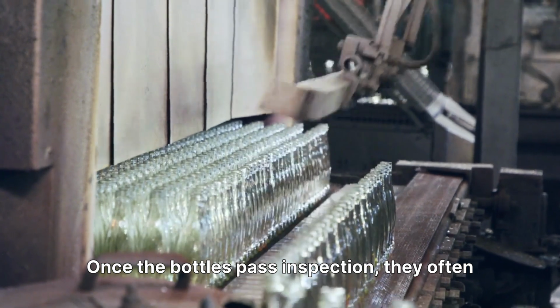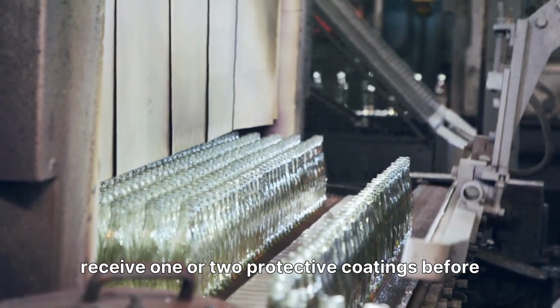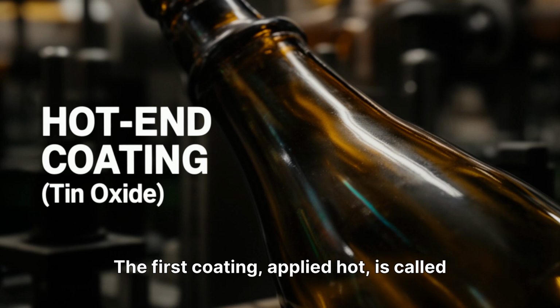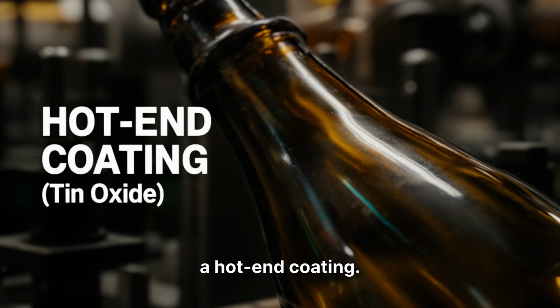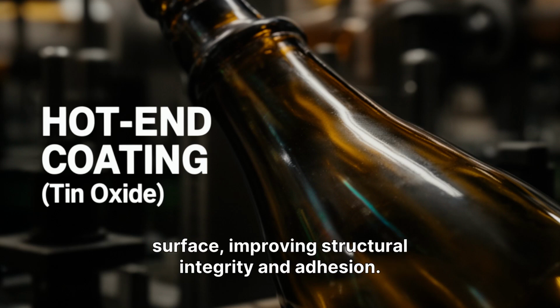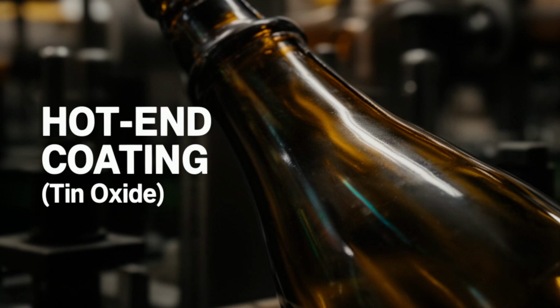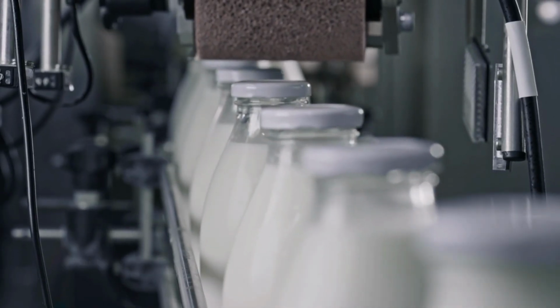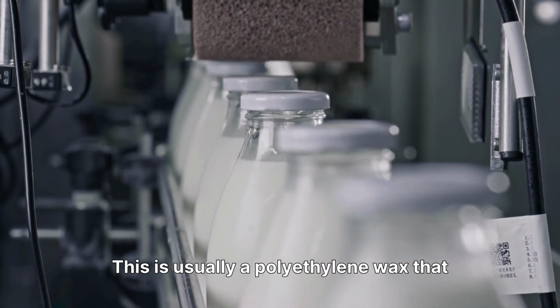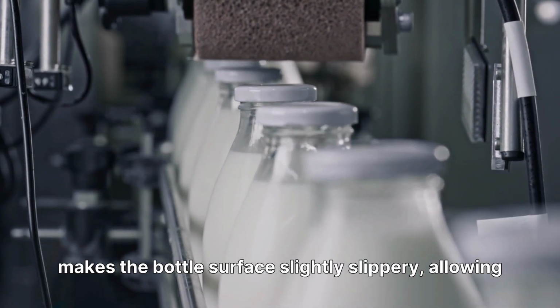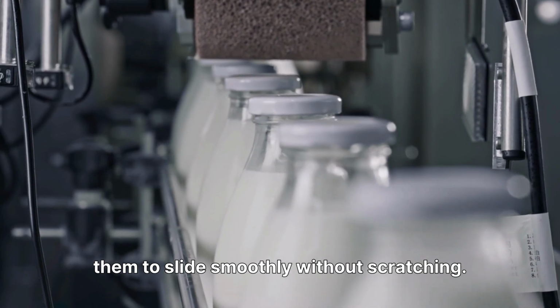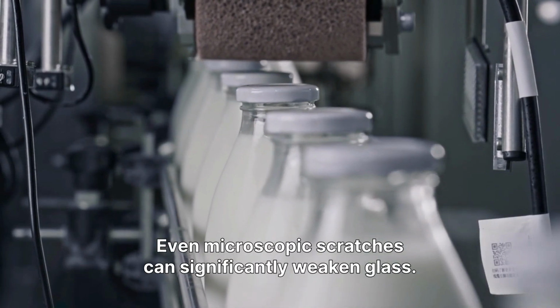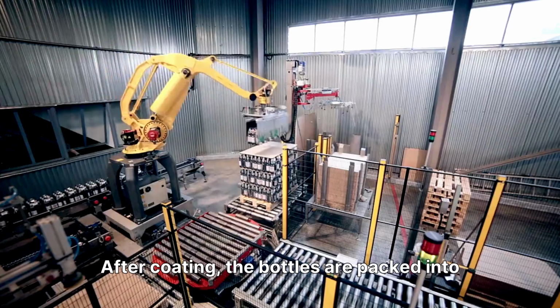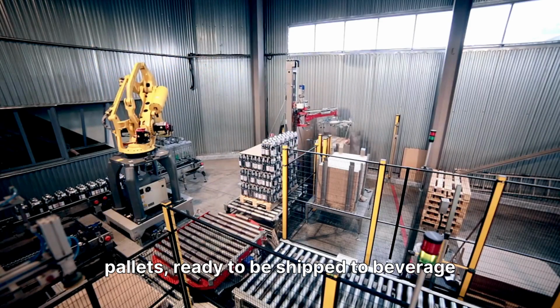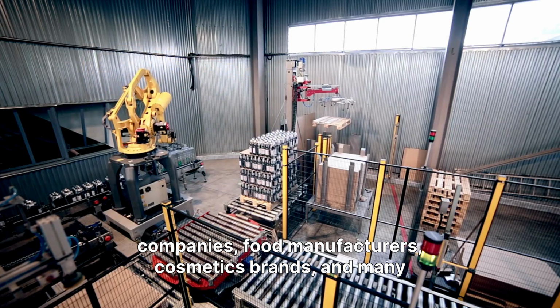Once the bottles pass inspection, they often receive 1 or 2 protective coatings before leaving the factory. The first coating, applied hot, is called a hot end coating. This is typically a thin layer of tin oxide that bonds to the glass surface, improving structural integrity and adhesion. After annealing, a second cold end coating is applied. This is usually a polyethylene wax that makes the bottle surface slightly slippery, allowing them to slide smoothly without scratching. Even microscopic scratches can significantly weaken glass. After coating, the bottles are packed into pallets, ready to be shipped to beverage companies, food manufacturers, cosmetics brands, and many other industries.